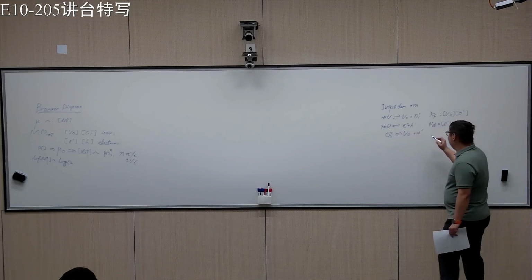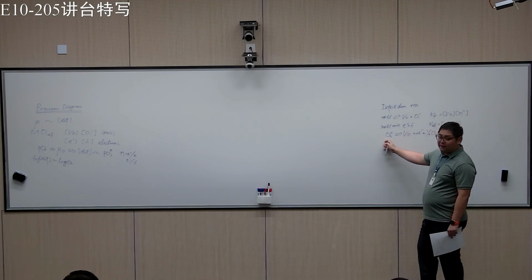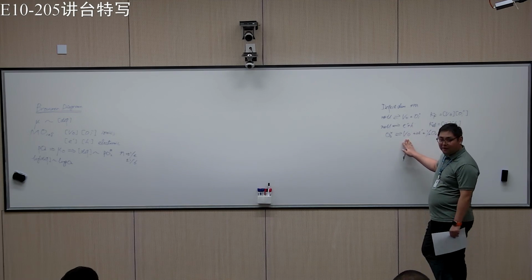And of course, when the oxygen leaves the sample, it goes to the gas phase. So there's also a constant associated with that. If we neglect the fraction of this one, because usually we treat a dilute system so that mostly the oxygen stays in place, and only a few become oxygen vacancies, we can write something like this.